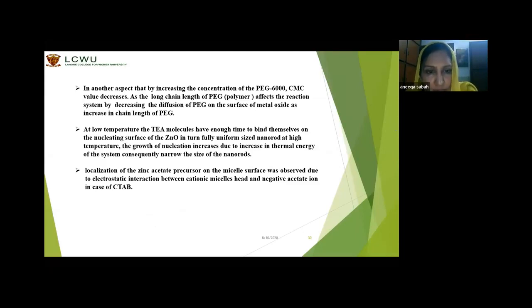At low temperature, TEA molecules have enough time to bind themselves on the nucleating surface of zinc oxide, giving uniform sized nanorods. At high temperature, the growth of nucleation increases due to increased thermal energy of the system, consequently narrowing the size of the nanorods.